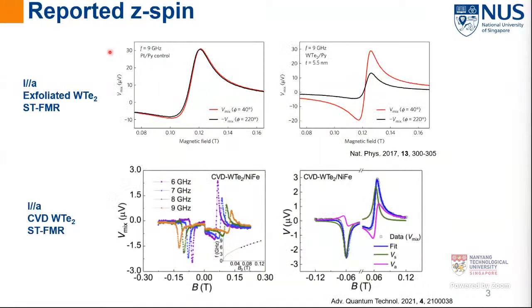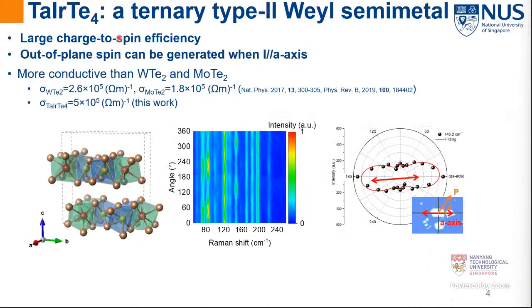Currently, the Z-spin from Weyl semimetal is observed in exfoliated tungsten telluride and also CVD tungsten telluride with the method of ST-FMR. Compared to the conventional binary Weyl semimetals, tungsten telluride and molybdenum telluride, their ternary family member is more conductive, which is supposed to give a high spin conductivity. In this work, we use flakes mechanically exfoliated from a single crystal of Td phase TaIrTe4. With the help of microscopy, rectangular flakes were chosen and patterned into a Hall bar along the a-axis. Then the ST-FMR measurement is adopted for spin texture detection.